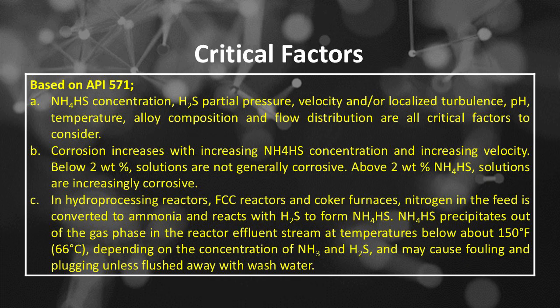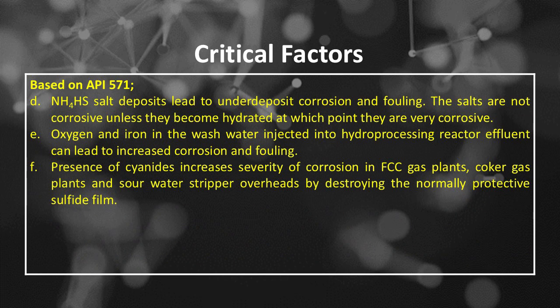C, in hydroprocessing reactors, FCC reactors and coker furnaces, nitrogen in the feed is converted to ammonia and reacts with H2S to form NH4HS. NH4HS precipitates out of the gas phase in the reactor effluent stream at temperatures below about 150 degrees Fahrenheit or 66 degrees Celsius, depending on the concentration of NH3 and H2S, and may cause fouling and plugging unless flushed away with wash water. D, NH4HS salt deposits lead to underdeposit corrosion and fouling. The salts are not corrosive unless they become hydrated, at which point they are very corrosive.